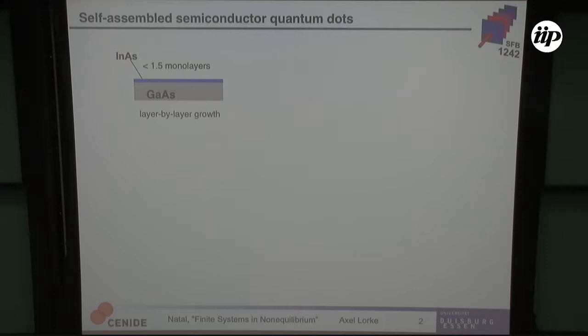Self-assembled semiconductor quantum dots have been around for now almost or more than 20 years. They form when you have two different semiconductors with different lattice constants, and you grow one on top of the other. First, the second semiconductor will adhere to the lattice constant of the substrate, but then under the right growth conditions and the right material combinations, at higher coverage, islands will form. And these islands are given by strain, interface interactions and things like that.